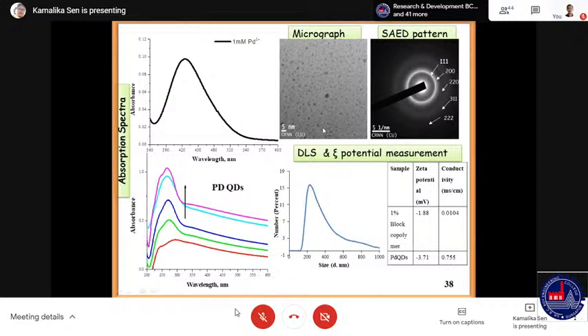Actually, I tell the students who are getting introduced to nanotechnology that if you place a grid on which you have put your nanoparticle solution and allow the electron beam to fall on it, the shadows of the nanoparticle fall on your experimental plate. But if you take the nanoparticle containing solution in the DLS setup, which is just like a UV visible setup, then you will measure the hydrodynamic radius. That means the nanoparticles surrounded by the hydrated environment. So the overall size seen by the instrument is higher. So you can see that there are particles with more than 200 nanometer size. That does not mean that your particles are of 200 nanometer size. They are surrounded by the hydration actually.